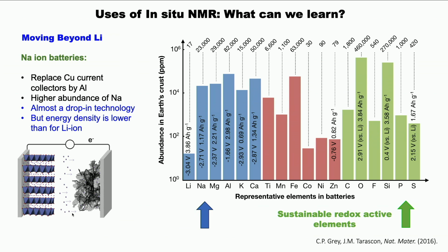So just to give you another example, I wanted to put carbon in as the theme in a lot of what I'm talking about. In sodium-ion batteries, you can't intercalate sodium into graphite. You can intercalate lithium, you can intercalate potassium, but sodium's the wrong size. And so if you want to go for a more sustainable technology, you've got to find a new anode replacement. The thing that people use for the replacement is a material called hard carbon, which is essentially a carbon that's heated up, that doesn't graphitize. It has enough defects in the structure that it doesn't form beautiful layers.